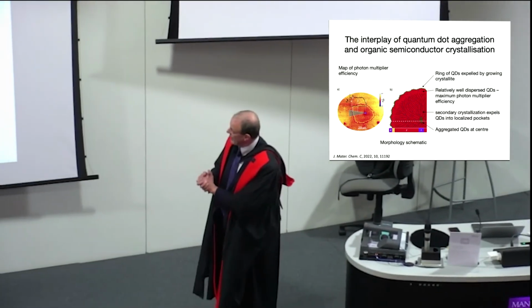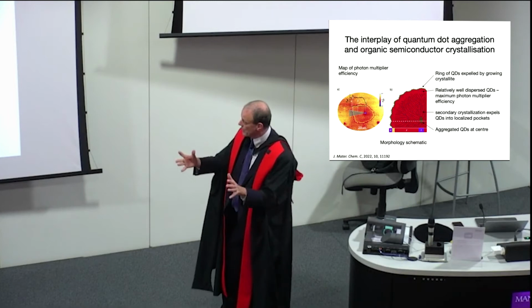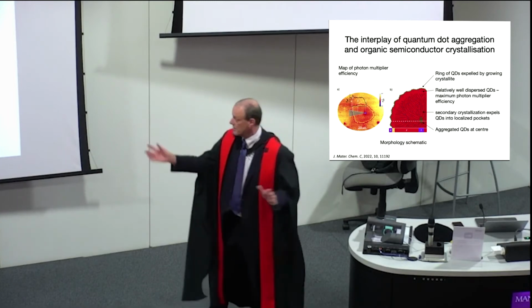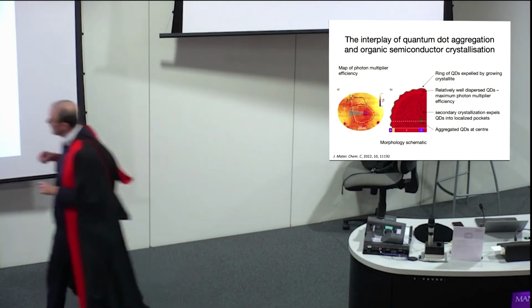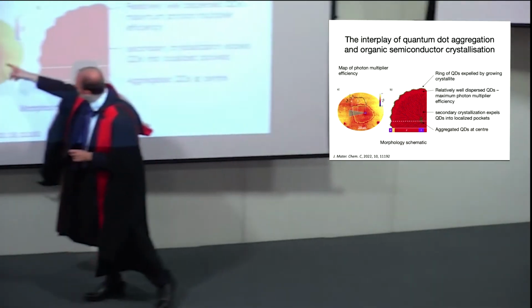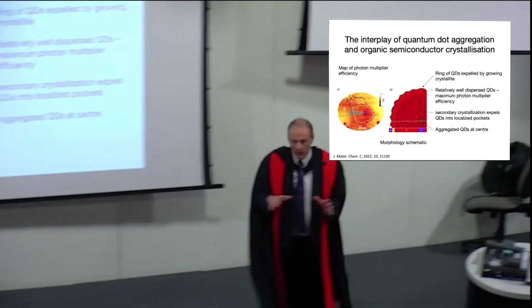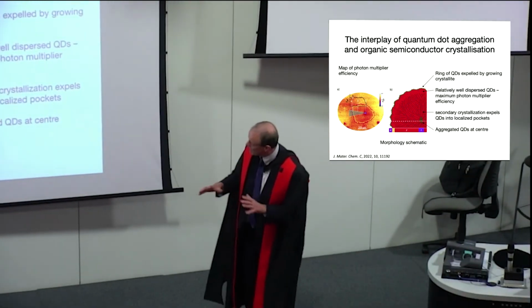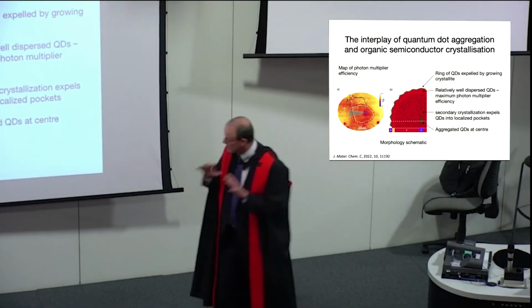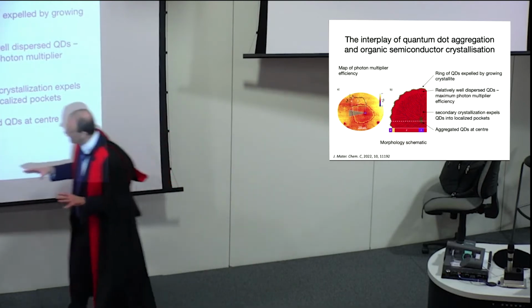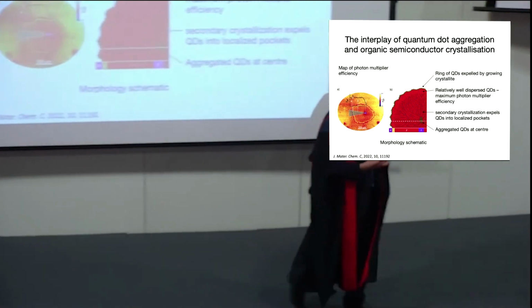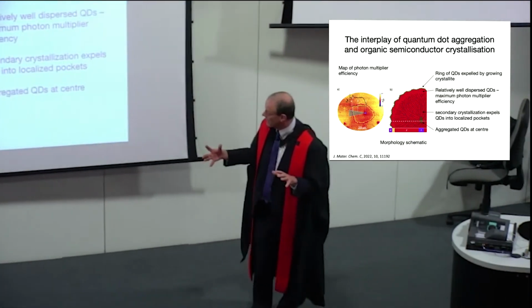So the sort of thing that you see, just to give you a very brief flavour of it, if you look at it, here's a sample. You mix up the quantum dots with the organic semiconductor, just spread it out, what do you get? This is actually a map of the photon multiplication efficiency. And so material scientists, or anybody who's certainly done any polymer science, will immediately recognise this. This is a spherulite. This is spherulitic growth. So you've got in the middle there an aggregate of quantum dots. A spherulite grows from the aggregate.